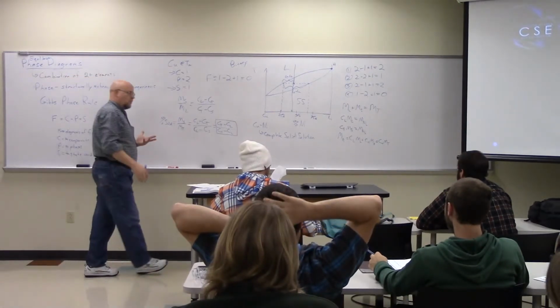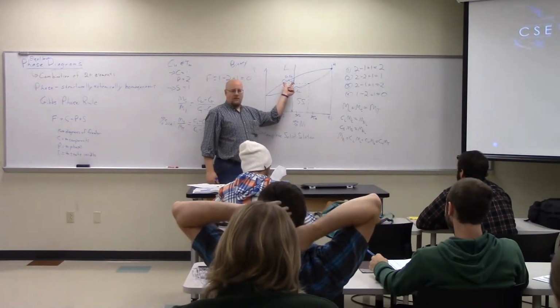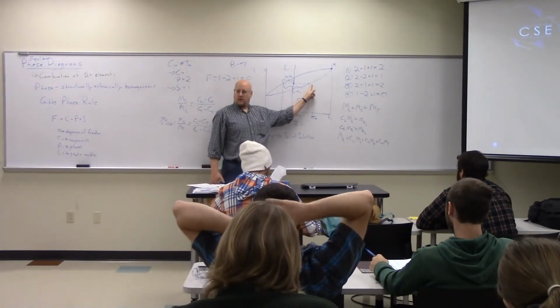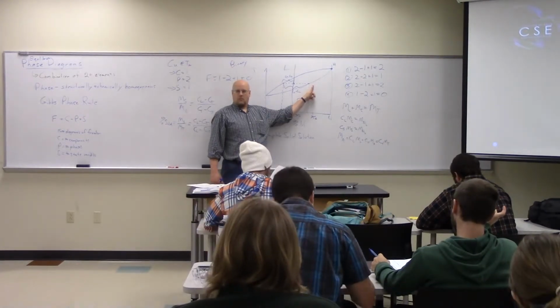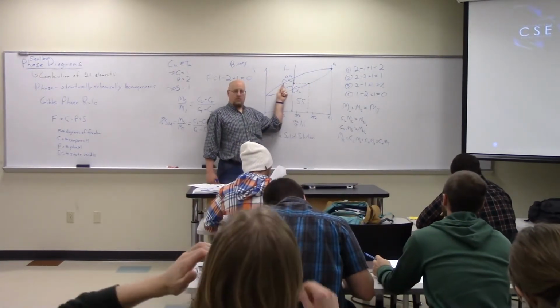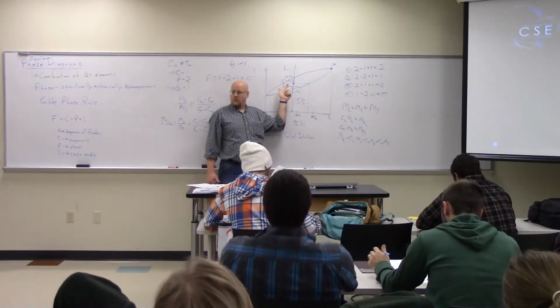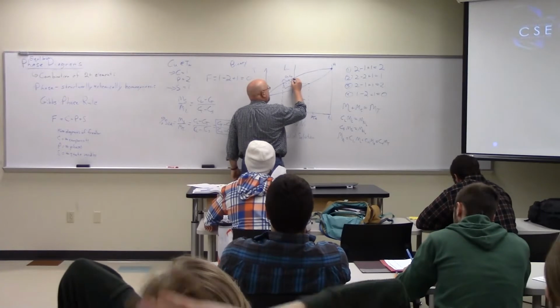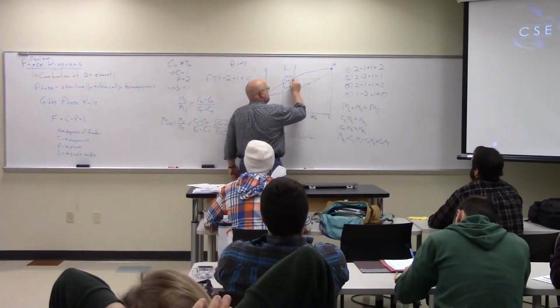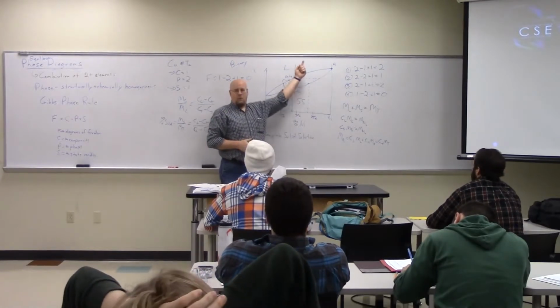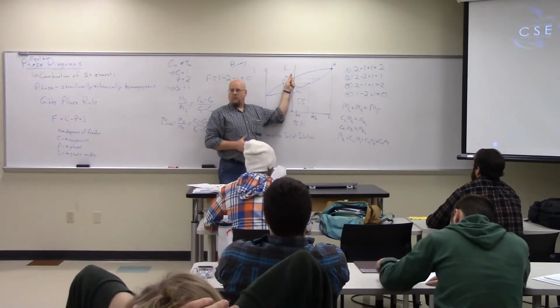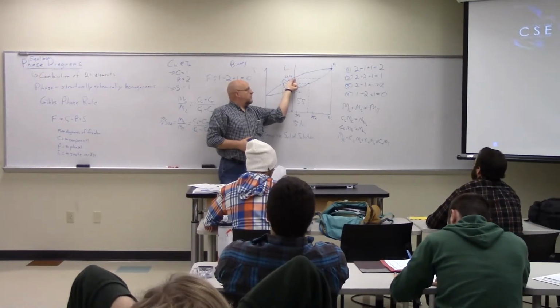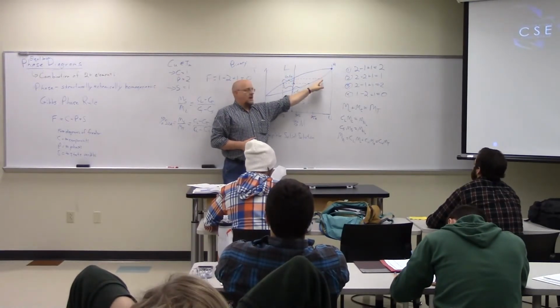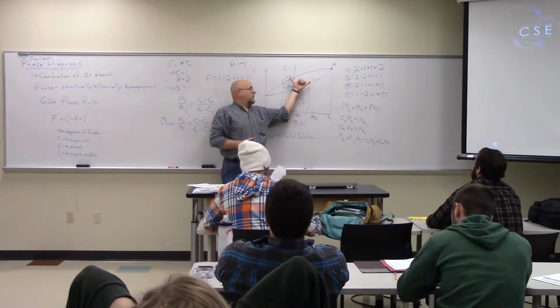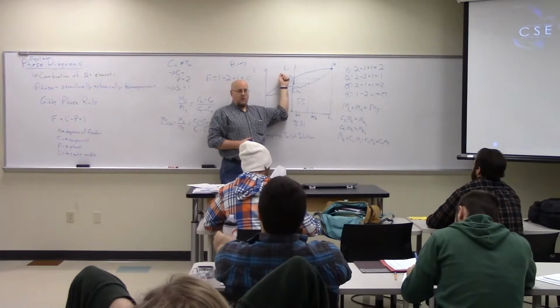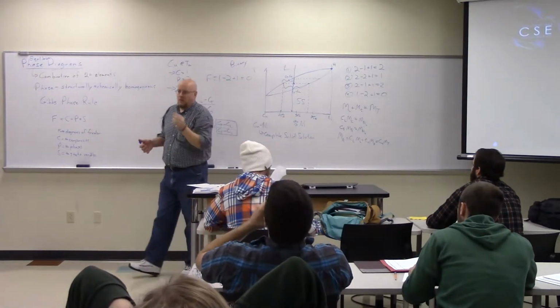It's the inverse lever rule. This side of the lever determines that weight percentage. And if I did it the other way, this side of the lever determines that weight percentage. Does that make sense? So when you first come through here, at this line, I had very little solid. It was mostly all liquid. I just started to form solid. So I have this little piece divided by the whole length, so you can find out how much solid I have. And the big long piece divided by the only slightly larger length gives me the amount of liquid. So I'm mostly liquid with a little bit of solid.